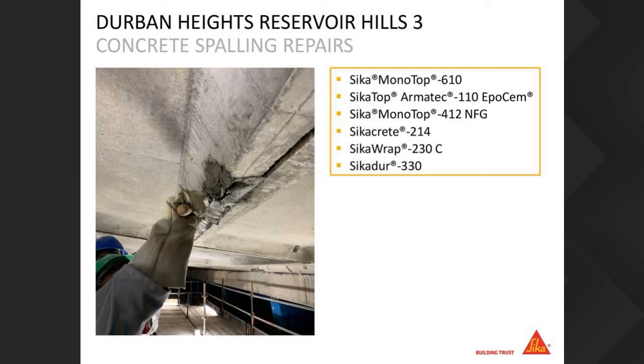We did use a bit of our Sika Crete 214 where we had to break through the roof structure, but that was only a few bags, not more than half a cubic meter, and that's structural microconcrete. Obviously, some of the rebar had bad damage and was replaced as per the engineer's instruction. Some of the beams and soffit area had to be strengthened with our SikaWrap-230C carbon fiber structural strengthening system in conjunction with our Sikadur-330 structural epoxy.